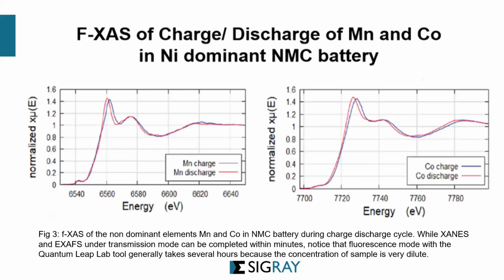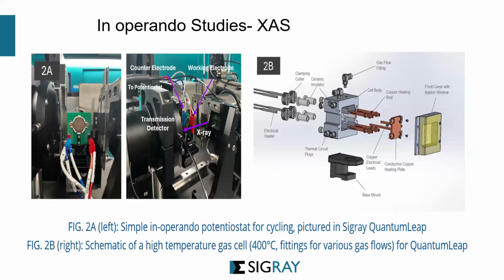So let's take a look at some of the studies for the NMC, looking specifically at manganese and cobalt in a nickel-dominant material. Here you can see that the manganese and the cobalt under charge-discharge cycle can be studied under the fluorescence mode. But the most important part that we want to share with you is, can you do operando studies using XAS, and do you have anything to prove that you have done that? And we have basically done that.